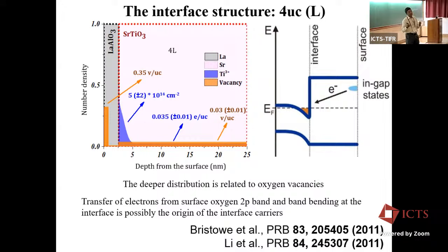So by pulling an electron out from there, what you're doing is reducing the affinity for oxygen to bond to lanthanum aluminate, and so the chances that the oxygen vacancy would be created is actually promoted by the fact that you're wanting to transfer an electron. So they work hand in hand, and the oxygen vacancy is the reality that forms, and it forms over here, a layer of.